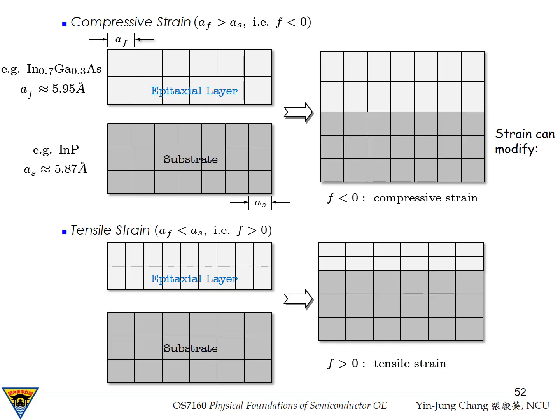So we see that the width of the unit cell shown here is larger than that of the unit cell shown here, while again, because of lattice effects, the lattice spacing in the direction perpendicular to the interface usually becomes slightly smaller. So the height of the unit cell shown here is smaller than that of the unit cell shown here.